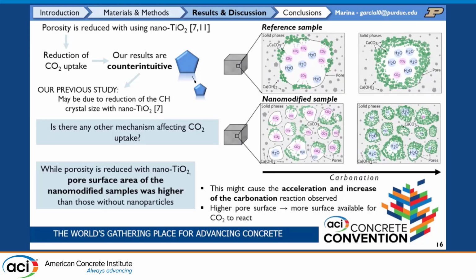And this is seen in this figure that I'm showing you to exemplify this. On the top, we have a pore of a reference sample, and on the bottom, of a nanomodified sample. Even though we may have the same overall porosity, because we're refining that pore structure, we have more surface, so the CO2 can react with more CH around that surface.